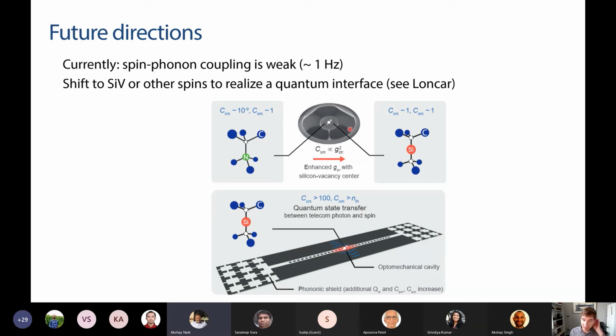Sure. Okay. And then another advantage, which is not obvious, is that the fact that our optical field doesn't overlap with the point of high stress in these devices was important for the experiment that we did. Because the really strong IR field, which is driving this mechanical motion, would actually have some effect on the charge state of these NVs, which might be a problem in these optomechanical crystal cavities. But there might be a way to work around that. But yeah, it did end up being sort of lucky that we were working with these devices for these experiments.